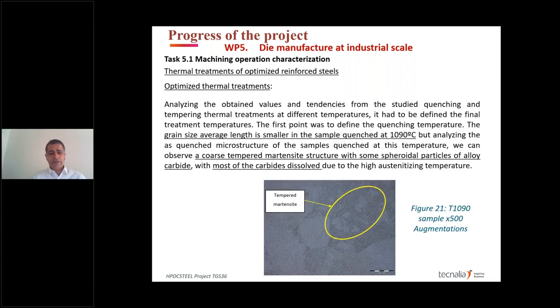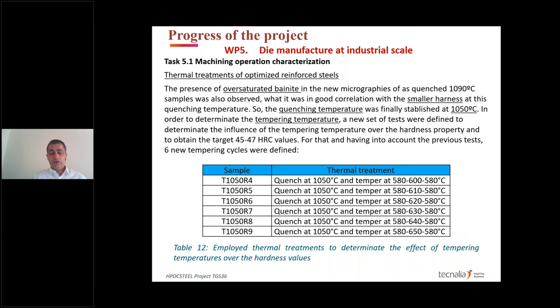And we also see that in the case of 1090 degrees, there was some coarse tempered martensite structure. So we think that because of the dissolution of some of the carbides, we have a decreased hardness on the final quenched samples. With these results, we determined the quenching temperature, but we wanted to test the temperatures in this interval that we have seen before.